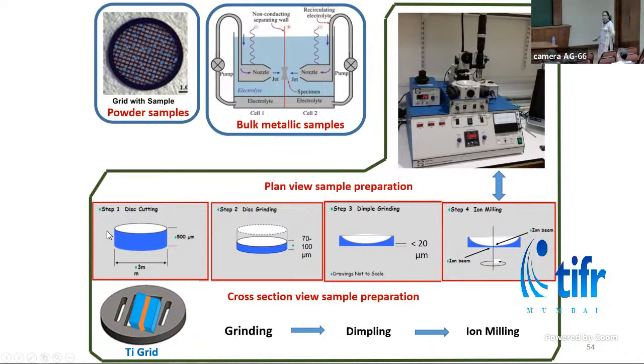Here we cut a 3 mm sample disc from the sample and then we grind the sample to 100 micron thickness. Then using a dimple grinder, we make a dimple in the sample. Then the sample left is around 20 micron. Then by using focused argon ion milling, we create perforations in the sample, which are electron transparent.